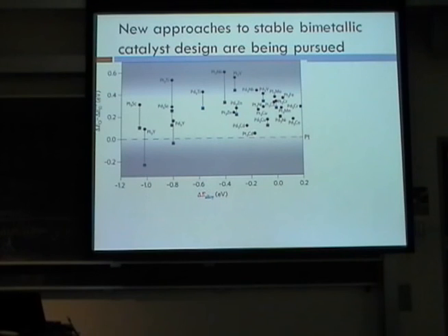They would look, as one of their metrics, using density functional theory calculations, at how strong the energy was for forming the particular alloy. The more negative it was, the more likely it would be in a very strong thermodynamic well and therefore be stable over long periods of operation time inside a fuel cell. And they were able to couple that with the analysis of how strongly absorbed the oxygen was compared to what the case is on platinum.